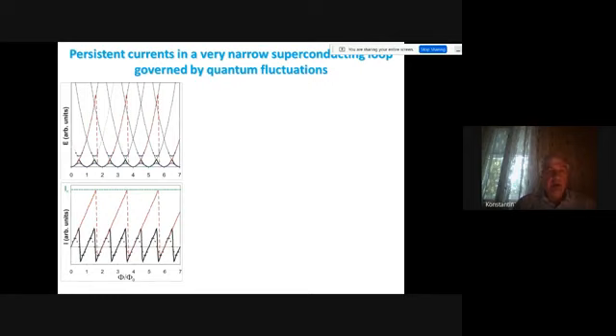So let me remind you that if we take a macroscopic superconducting ring, the flux is quantized there. And the dependence of energy on magnetic flux in units of the superconducting flux quantum is a periodic function: a quantum state with vorticity equal to 0, a second parabola with vorticity equal to 1, 2, 3, and so on. So if the sample can freely go from one state to another, it might go very high in energy and then jump to the ground state. Again high in energy and again to the ground state. So the transition might have a large periodicity in magnetic flux.